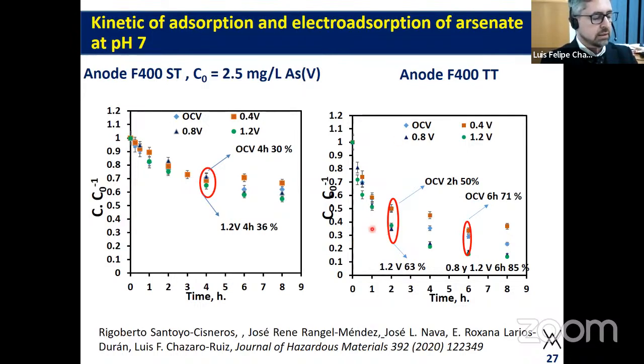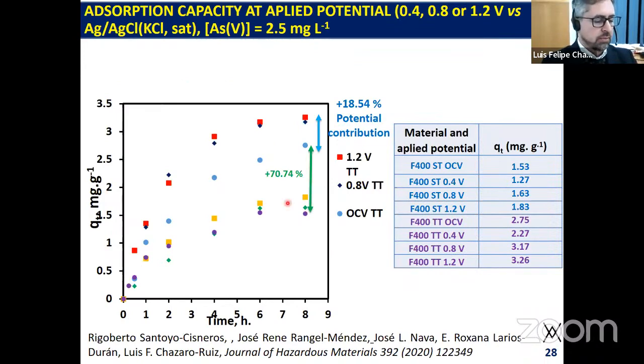This indicates that an overlap of the double layers has occurred at this potential, and then the pores of the materials are obstructed, or obstructs the entrance of the arsenate. No? So, and in the other cases, like 0.8 and 1.2, you can see this increase in the adsorption capacity. So then the thermal treatment of the material provided a contribution of 70% of the adsorption process, while the potential or polarization of the electrode contributed 18.5% to the increase in the adsorption capacity here.